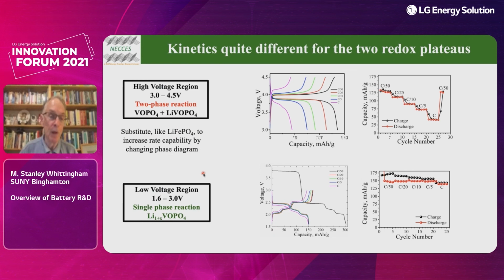Let's now look at the low voltage region. So we first put in our 2 lithiums down here, then we cycle it in this region. And now you can see whether we're at C/50 or C rate, the capacity is exactly the same at 150, which is the theoretical amount. The difference in these curves is just the IR loss and diffusion limitation we suspect. And you can see here's the lithium intercalation, essentially flat for all rates. You'll notice here, though, we have an issue.